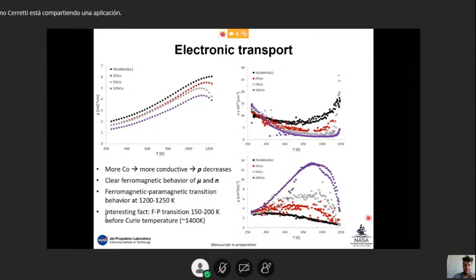This is also interesting to see when we analyze the charge carrier concentration and the mobility. Cobalt is a ferromagnetic material, and has a transition from ferromagnetic to paramagnetic. The temperature of transition of cobalt is 1400 K, but what we observe here is that between 1150, 1200, 1250, depending on the inclusion density, we observe the ferromagnetic to paramagnetic transition that is characterized by this increase in mobility, and then it decreases and starts being constant afterwards.